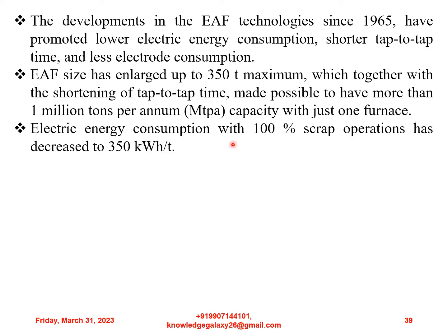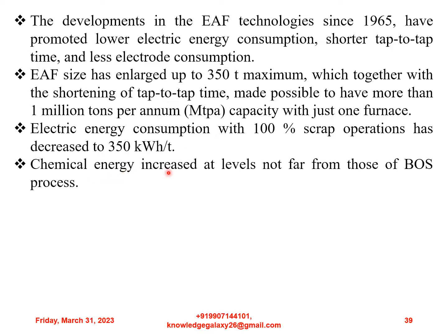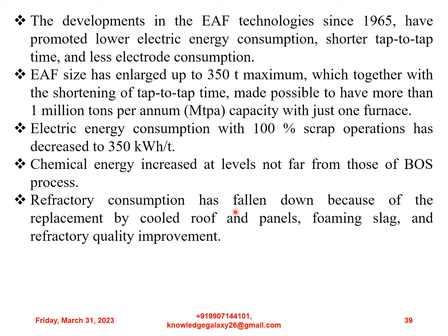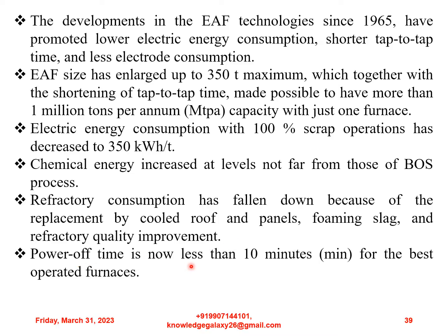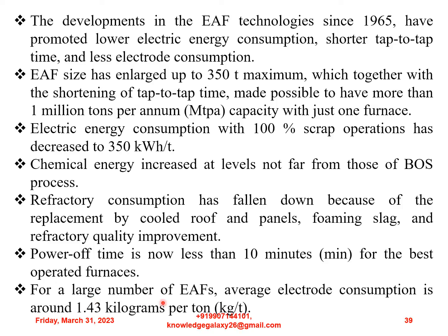Electric energy consumption with 100% scrap operations has decreased to 350 kWh per ton. Chemical energy has increased to levels not far from those of basic oxygen steelmaking processes. Refractory consumption has fallen because of the replacement by cooled roof and panels, foaming slag, and refractory quality improvement. Power off time is now less than 10 minutes for the best operated furnaces. For a large number of electric arc furnaces, average electrode consumption is around 1.43 kilograms per ton.